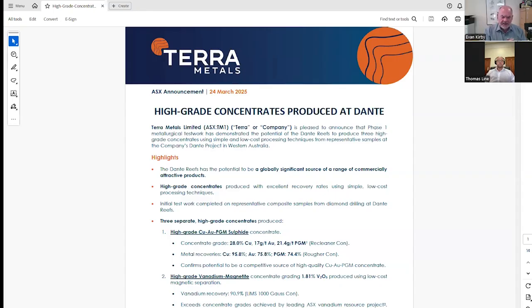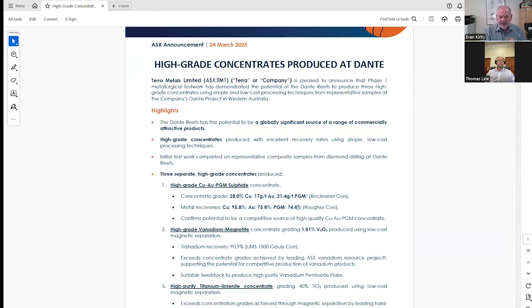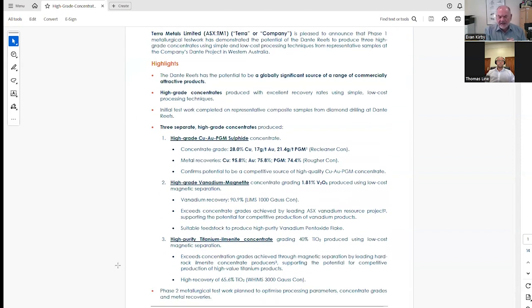We're demonstrating the ability to recover most of the copper and platinum and gold to a saleable concentrate, as well as that, produce a magnetite concentrate with very high vanadium content and low silica content, making it extremely suitable for processing with conventional vanadium technology to high purity vanadium pentoxide flake. And the magnetic fractionation has achieved very good recoveries of titanium to a 40% ilmenite concentrate.